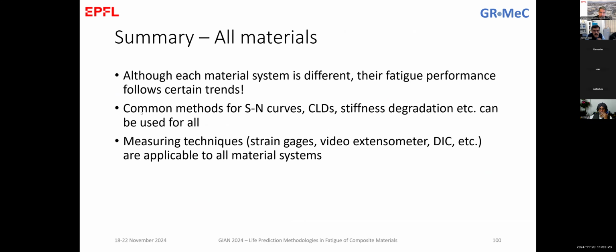So with this I summarized. The conclusion is, as we said before, that we have measurement techniques for everything, and we have common methods to simulate material behavior independent of the material system, and more or less all materials, this is what we can also keep in mind, follow the same trends. The SN curve is more or less a power curve on the SN plane. The stiffness degradation has this behavior of sigmoid degradation up to the end. The constant life diagrams are not Goodman-like diagrams, but are, depending on the material system, might be more tension dominated or compression dominated, and so on.